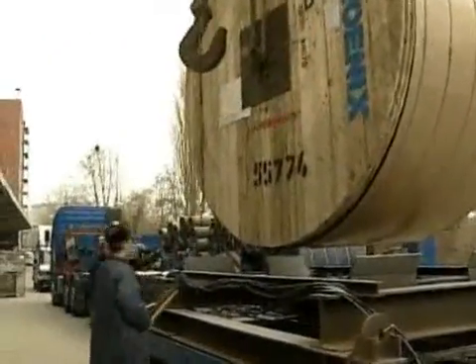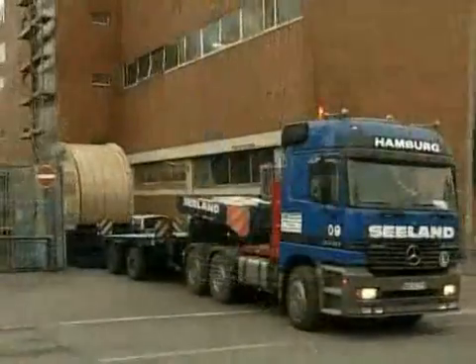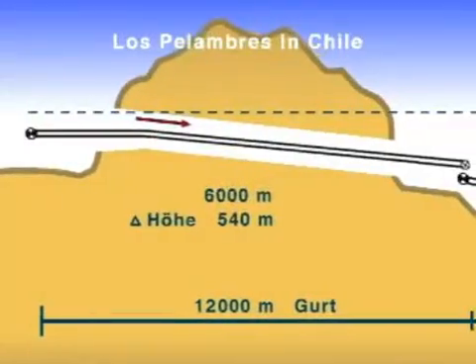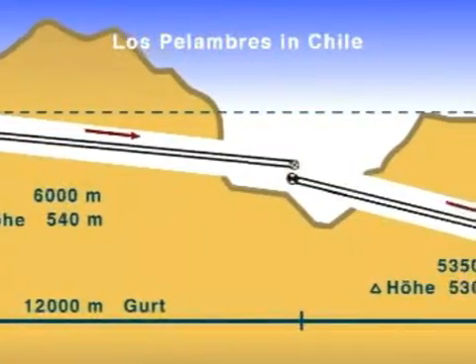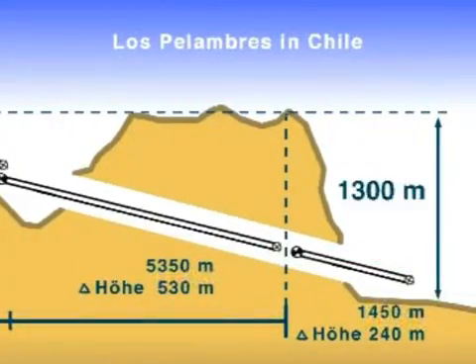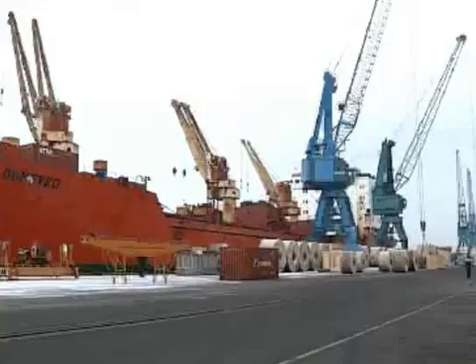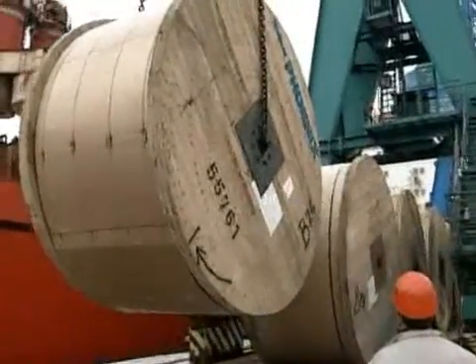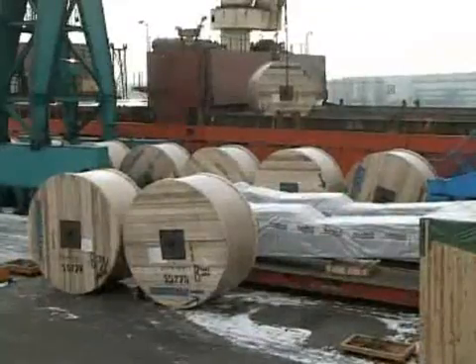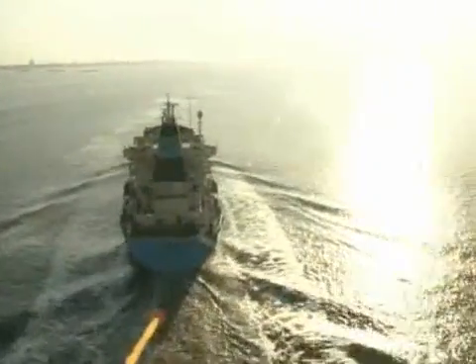In 1998, Phoenix supplied a Phoenix cord ST7800 for the Los Pelambres copper mine in Chile. This conveyor belt breaks all the existing Phoenix world records — it is the strongest conveyor belt anywhere on earth. The belt splice fatigue strength, as per DIN 22110, is 4,213 newtons per millimetre, which equals 54% of the minimum belt breaking strength. During belt operation, the belt splices are monitored by the groundbreaking electronic system PhoenixCare SC. The ST7800 is also equipped with PhoenixCare transponders and sensor loops embedded in the rubber cover. These electronic devices enable Phoenix to monitor online the belt's present condition anywhere in the world where Phoenix conveyor belts do their vital job.